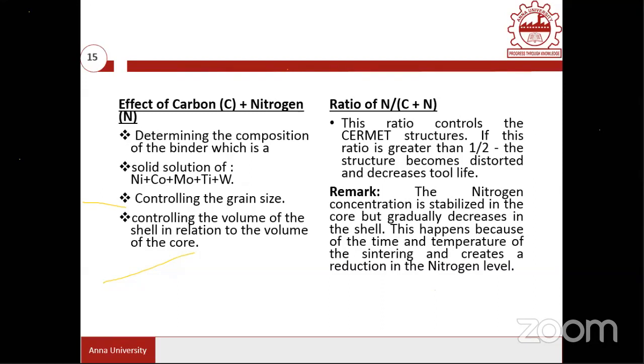And the ratio of nitrogen to carbon plus nitrogen is also very important. In any case, if you take a different composition, the ratio of nitrogen to carbon plus nitrogen should not exceed 0.5. If it exceeds 0.5, there will be a distortion in the cutting tool. Also, the nitrogen concentration is stabilized in the core but gradually decreases in the shell because of a reaction, as well as, sometimes because of the prolonged sintering time, the nitrogen at the outer surface will also be vaporized. That nitrogen elimination would be there. So that is also another issue here.